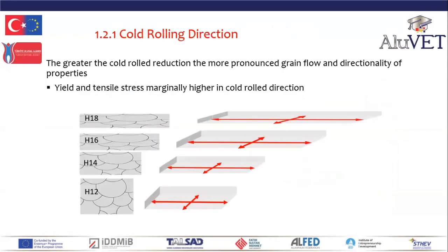Now, as we work harden, we compress the grains and plastically stretch or grow longitudinally in the direction of deformation, cold rolling. So we're inducing directionality. The directionality means that the mechanical properties, yield and tensile strength, will be slightly higher in the longitudinal direction than in the transverse, whilst ductility will be higher in the transverse direction.